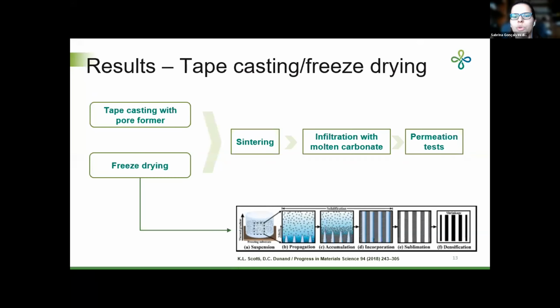So in this work, we also use the same type of powders, Gadolinia-Doped Ceria as ceramic powder and sodium lithium carbonate to infiltrate. Basically, the samples were prepared by tape casting using rice starch as pore former, and also porous matrices were prepared by freeze drying, which is a technique that uses water and rapid unidirectional freezing to produce aligned pore structures. Both samples were sintered, infiltrated with molten carbonate, and the permeation tests were performed.